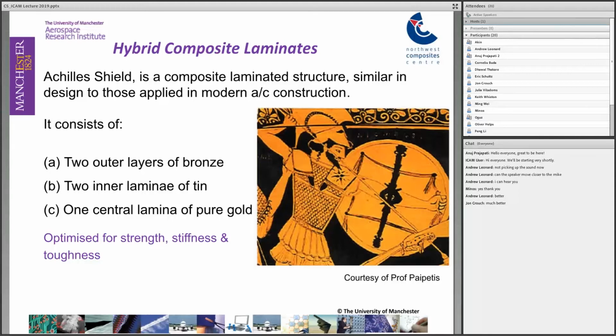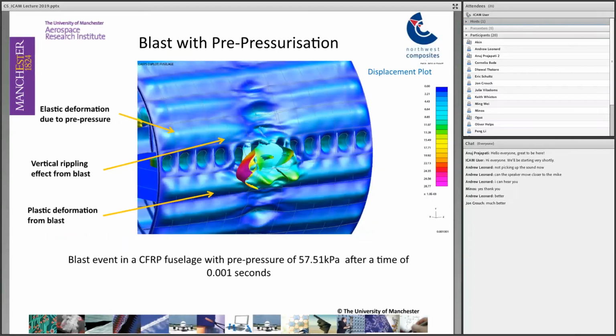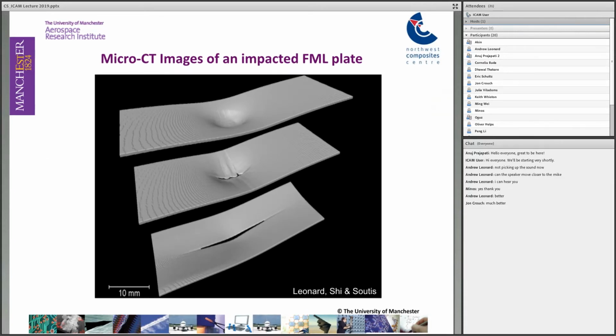So based on this principle, we can see the carbon fiber composite on its own under a blast event in a pressurized aircraft cabin, where a big hole is created, and we don't want that. We don't mind getting damage, but we do mind getting perforation. And if we compare that with a fiber metal laminate under a high velocity impact, we're going to see that the aluminum layer in this case has absorbed all the energy from the blast. Yes, we have inner damage in the other layers, but we managed to avoid perforation.